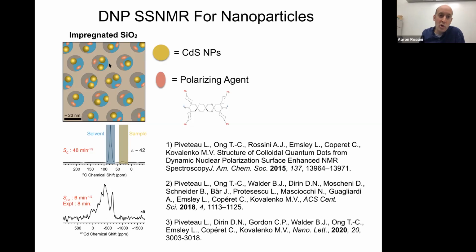If you just try to add your polarizing agent to the nanoparticle solution and freeze it, the nanoparticles will precipitate out as the solution cools down and freezes, and you'll end up getting phase segregation between the nanoparticles and the radicals. So by doing this trick with silica, you can prevent that phase segregation. This allows you to get pretty good DNP enhancements. We have an enhancement of about 40, which we can measure from the carbon NMR signals of the ligands that cap the cadmium sulfide nanoparticles. And then we can obtain a cadmium NMR spectrum in about 8 minutes. For this study, we used cadmium sulfide nanoparticles, and I'll talk more about what this cadmium-113 NMR spectrum means in a little bit.